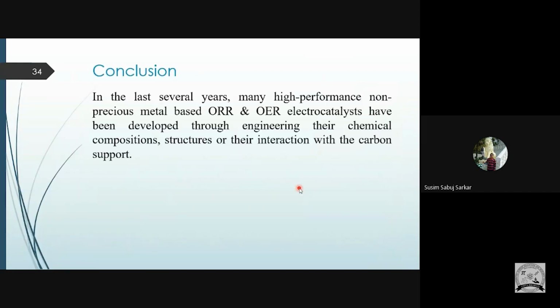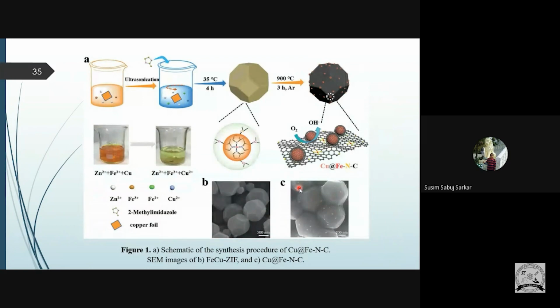Okay, so, sorry, this slide came before. I'm giving an example of forming a metal organic framework based electrocatalyst. People are doing this synthesizing procedure, the synthesis of Fe-Cu ZIF. First, they use ferrous and copper. People saw that iron-based zinc organic zeolite imidazole framework gives very good activity. As I showed in the volcano plot, copper also has activity. So one research paper was trying to make this Fe-copper mixed ZIF.